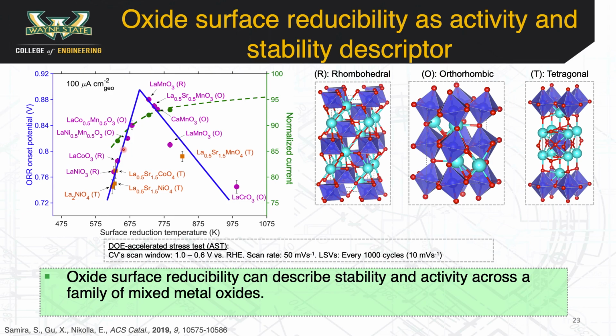I initially set off with asking the following question, where I wanted to describe both the activity and stability of these oxides. Although I mainly described activity thus far, I'll shed light into describing the stability of these oxides. What one can think of is oxides on the left leg of this volcano, characterized by low surface reduction temperatures, exhibit weak metal oxygen bond strength, thus can be easily reduced, while oxides on the right leg exhibit high surface reduction temperature, which suggests challenges with reducing such oxides.